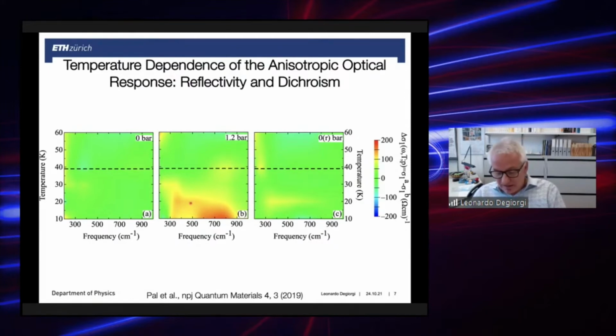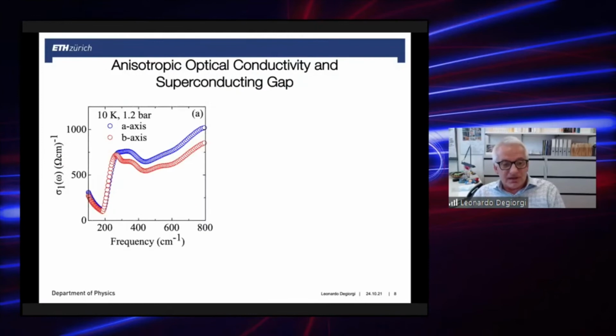So let me now try, going toward the end of my talk, to elaborate a little bit on this energy scale. So let me show you the measured real part of the optical conductivity down in the far infrared, here for the state at the largest applied stress. As I said before, you see here this rather important and substantial anisotropy in the optical spectrum between the two crystallographic axes. You may appreciate here this razor-sharp onset of absorption. This is the typical behavior for so-called s-wave-like superconductors, where the gap, although maybe anisotropic, opens on the whole Fermi surface.